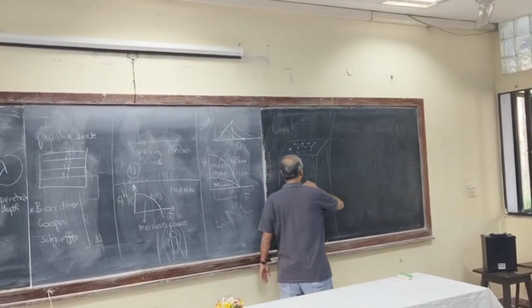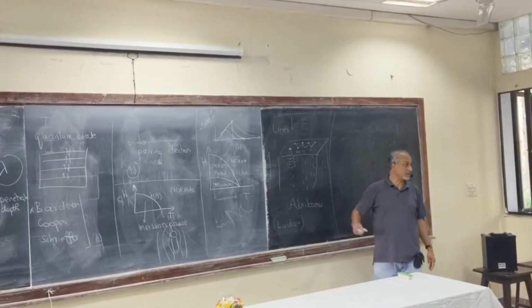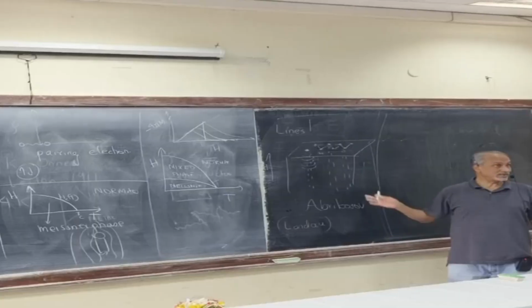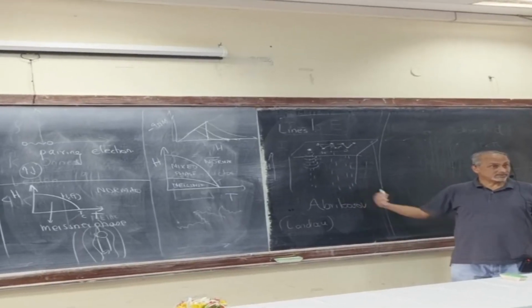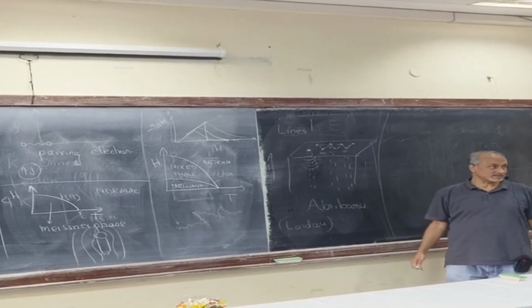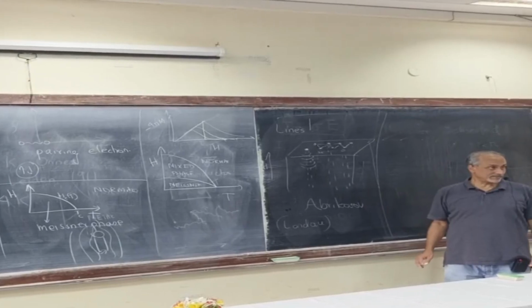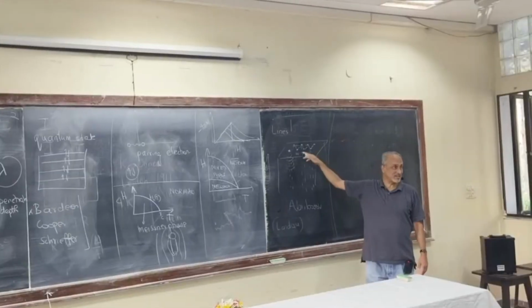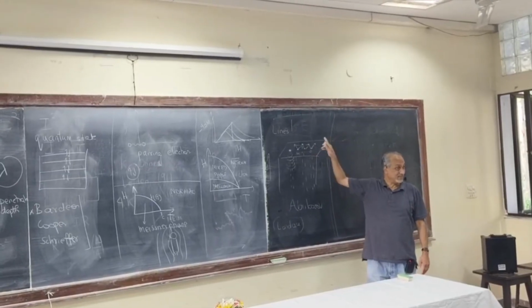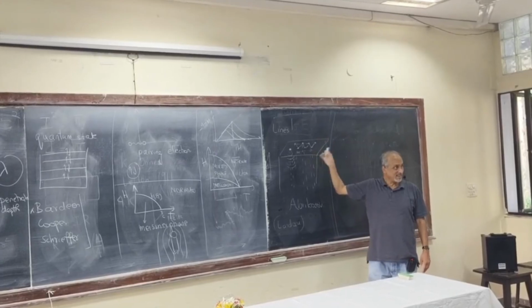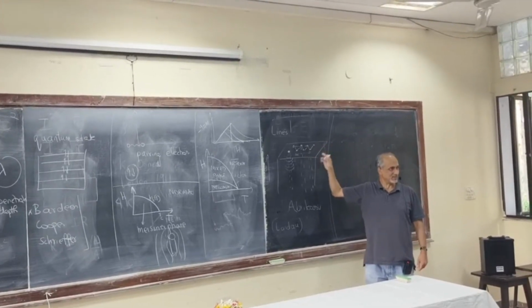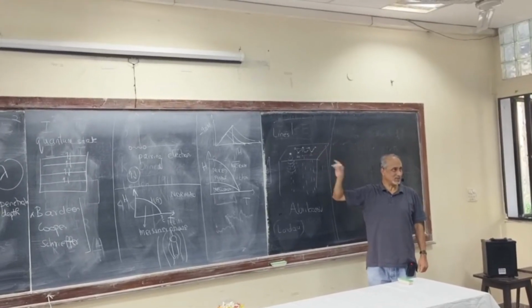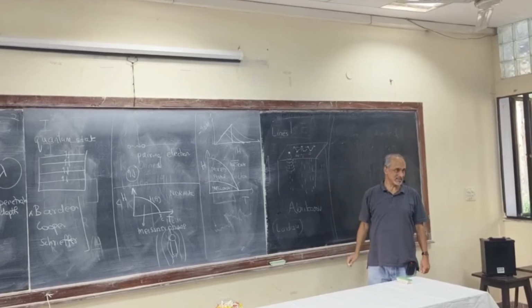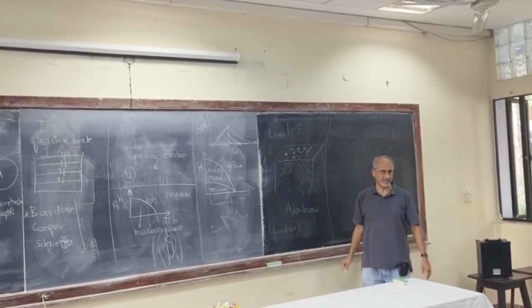But it's an amazing idea. He discovered it theoretically, not experimentally. He derived this behavior from equations for superconductors. He was able to show that they formed a triangular lattice. Actually, he made a mistake there. He first showed that they formed a square lattice. It had to be corrected a few months later by someone who said, "No, the triangular lattice has a lower energy than the square lattice," and then he made it better. But everything else was there in that case.